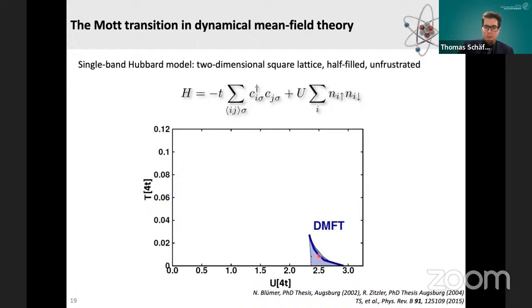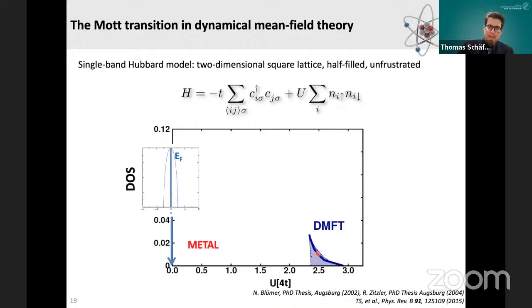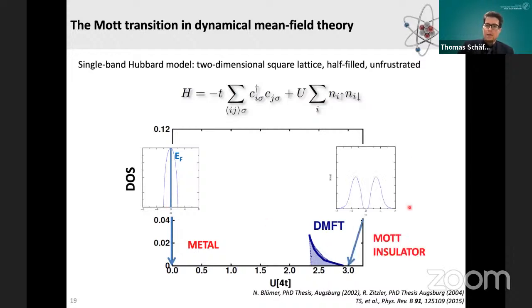Now you can see that we get here a region of the phase diagram shaded in blue, where we get a so-called first order phase transition between a metal at weak coupling, so at low U, and you can see this by plotting the density of states here again, and you have weight at the Fermi level. And on the right-hand side, a so-called Mott insulator. And now you see that we didn't change the band structure of this model. We still have, in the non-interacting limit, one band, but now all of a sudden, with a high U value, we get two bands, namely a so-called lower Hubbard band and an upper Hubbard band. These two bands are split, and we don't have weight at the Fermi level. So we have an insulator.